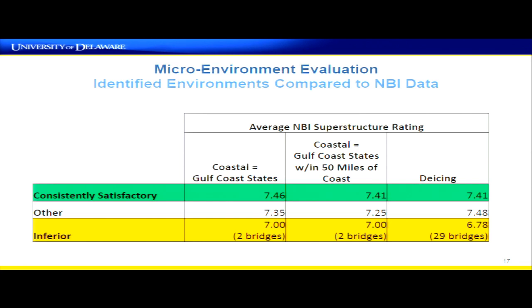For the de-icing, it was no surprise that there's not as good a correlation here, again because of the volume of data we looked at compared to the samples of bridges that actually exist. But we did find that the average rating of the bridges in that consistently inferior environment was statistically significantly lower than the rest of the bridges in that region.